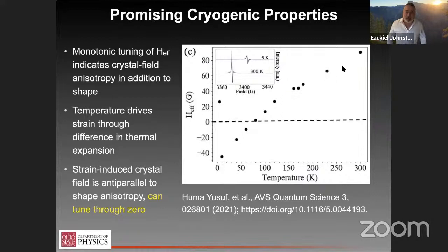And so this data actually came in advance of the intentional strain tuning, which is looking at, again, the magnetic resonance line width effective, or equivalently, the effective anisotropy field as a function of temperature. And so you can see that this tunes through zero to a negative value. And the magnitude of this tuning is enormous. So this is no longer, I apologize, in magnetic resonance, we bounce back and forth between frequency and field representations. So a typical line width in terms of field is 2 to 3 Gauss. So you can see this line width tuning is over 100 Gauss. So 40 or 50 line widths of tuning as the difference in thermal expansion coefficient between the thin film and the substrate drive a very large strain in the system.